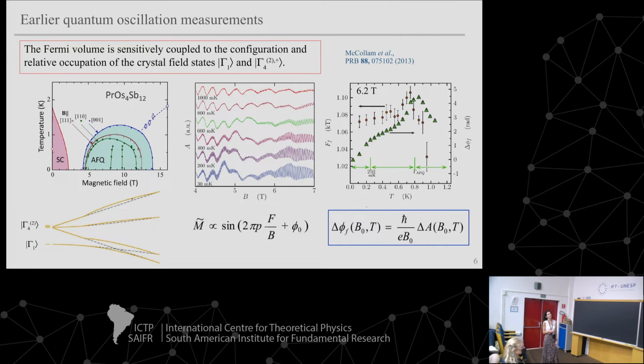But there's also a phase of the quantum oscillations, and this is quite a neglected quantity. But the phase is also proportional to the cross-sectional area of the Fermi surface, and just to cut the story a little bit short, the change in the phase as a function of field or temperature is proportional to the change in the Fermi surface cross-sectional area as a function of field or temperature. So if the phase increases, the Fermi surface is growing. And if the phase decreases, the Fermi surface is shrinking. So that's basically what we're looking at.